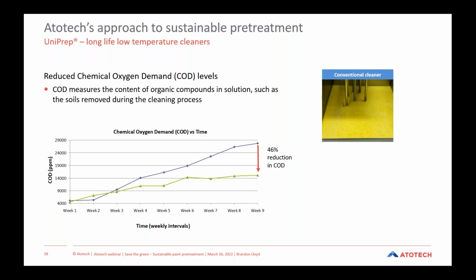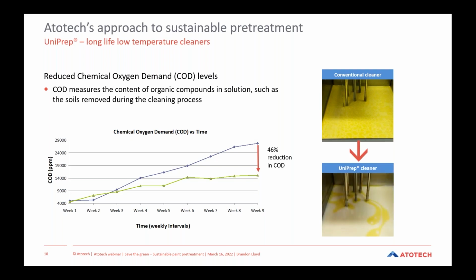So here is just an example of a conventional cleaner system exhibiting a high amount of surface oil on top of the degreasing solution. And then with the UniPrep cleaner system, you can see that the amount of oil is significantly decreased with that capability of being able to naturally degrade those oils.